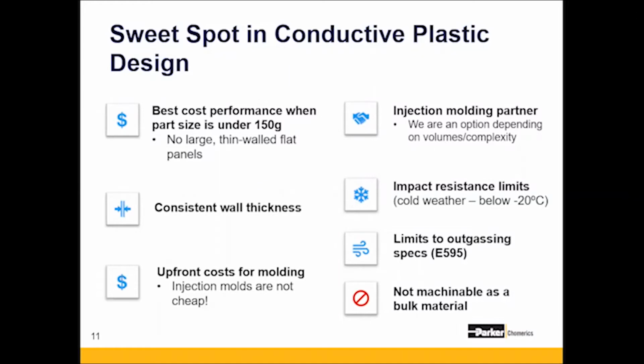And while there is some upfront cost in buying an injection mold, there are a lot of volume-based benefits for programs that require higher volumes. So for example, working with an injection molding partner is actually the best course of action, especially with those partners who often work with engineered polymers. And depending on the volume and complexity of those parts, Chomerics can be a partner. So not only do we manufacture the conductive pellets, but we can also do the molding in-house. Yeah, and so you're going to see diminished properties at lower temperatures below -20°C. There's also limits to outgassing, but this isn't specific to conductive plastics from Chomerics. This is across the board, so there will be limits to that.